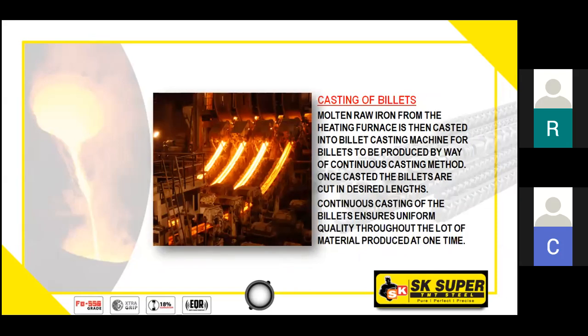What happens in the billet manufacturing process? This molten iron at a temperature of 1650 degrees is put into a bucket, from where it has two nozzles from below, beneath the bottom of the bucket, of the size of 100 mm by 100 mm or 115 by 115 mm. Normally for TMT, the billet sizes used are 100 by 100 and 115 by 115. The normal length is 2.44 meters, but depending upon the size of the bar to be manufactured, the billet length has to be adjusted for minimal wastage of the steel.